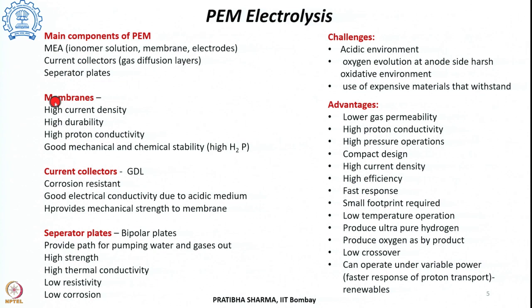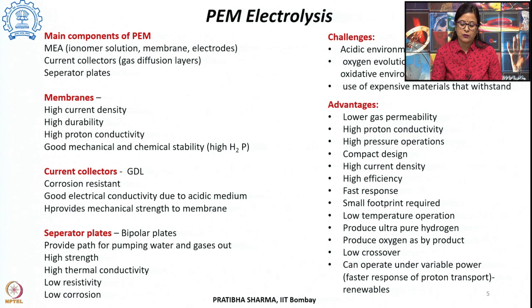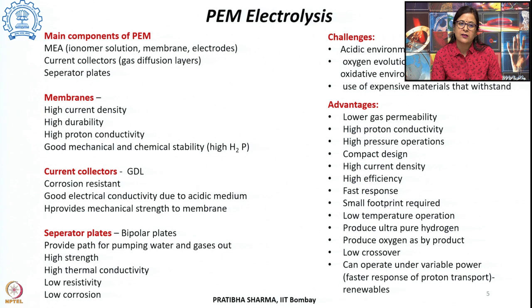The membranes require high current density, high durability, good proton conductivity, and mechanical and chemical stability. Because of the MEA's structural integrity and mechanical stability, the two compartments — the cathode and anode sides — can work at differential pressures. Hydrogen can be evolved at up to 70 to 80 bar while oxygen is at ambient pressure. Due to chemical stability, crossover and intermixing of product gases is much less in PEM electrolysis.